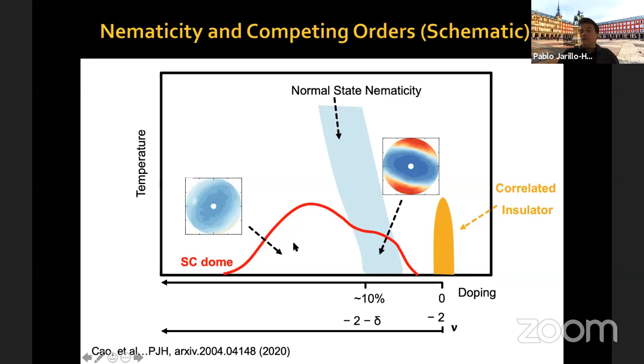That happens actually for all of the samples where we have done this in-plane magnetic field measurement, which takes many months, so we don't always do them. But all of the samples, 6 and counting, where we have made these in-plane magnetic field anisotropy measurements, all of them exhibit this nematicity everywhere in the superconducting dome for magic angle graphene samples, okay? Now, for these samples that exhibit this normal state resistivity anisotropy, the orientation of this nematic axis in the superconductivity evolves gradually with density in this region, but as we reach the region where we have this normal state nematicity, the superconducting axis strongly reorients itself.